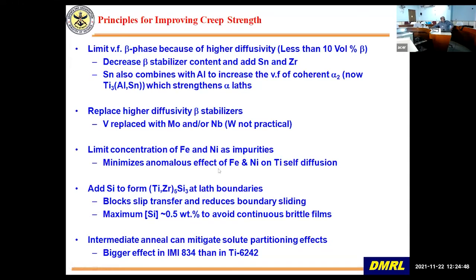Then the other thing that you have to be careful about is that very low amounts of iron and nickel can affect your creep properties, because iron and nickel enhance titanium self diffusion, and very, very small amounts of it cause anomalous diffusion, and that is why the creep properties get compromised. So you have to be very careful. So I will show you this effect.